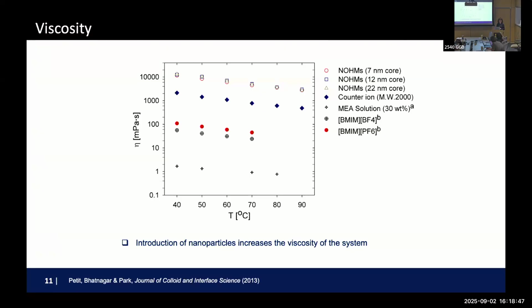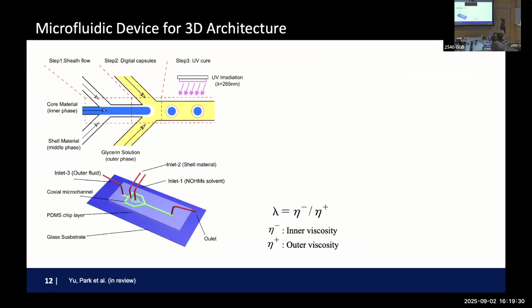So then I started thinking about this for a while. There's no way we're going to bring this viscosity down to here or even here. So we started thinking, well, can we create a lot of interfacial area, still benefiting from almost negligible vapor pressure and all that? So then, about that time, my friends at Lawrence Livermore National Lab, Roger Aines' group, started encapsulating salty solution. That was one of the CO2 capture technologies. They were doing dissolution and crystallization of salt solution in an encapsulated system. I thought that was really interesting. So I thought, well, our sticky honey-like material, if we can chop it apart and keep it apart, maybe this was the thing. So we started working with them on a microfluidic device, and now we have a whole other system doing this. The blue, we just put the blue dye so we know where our material is.